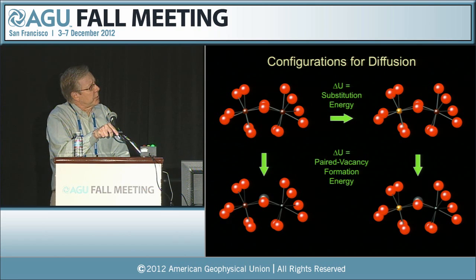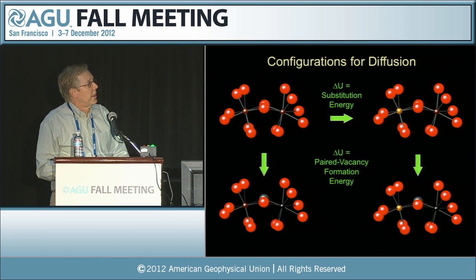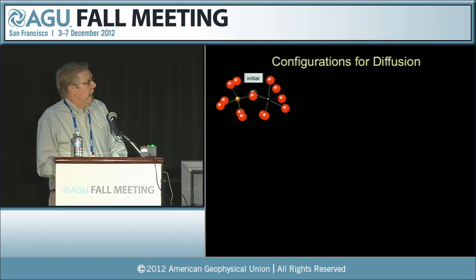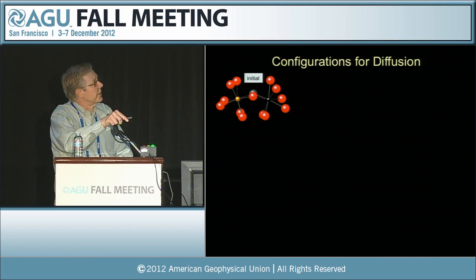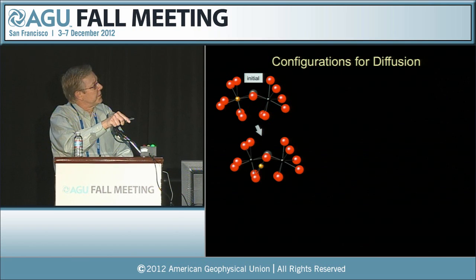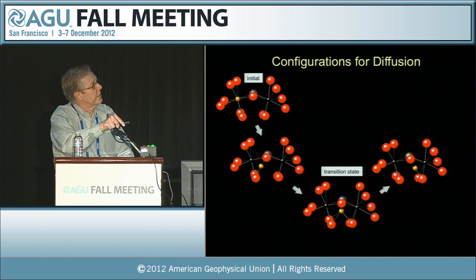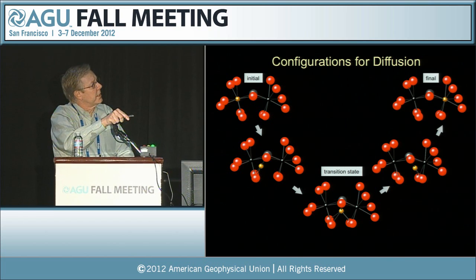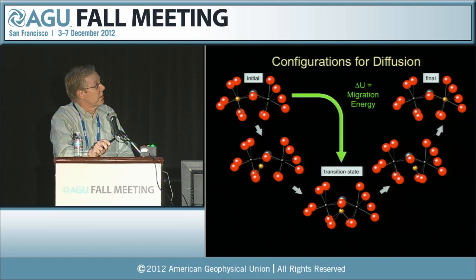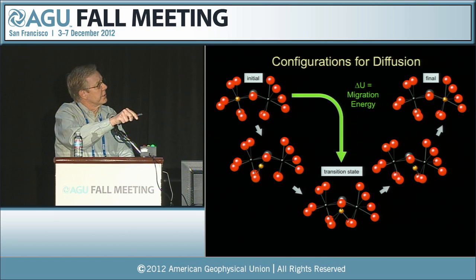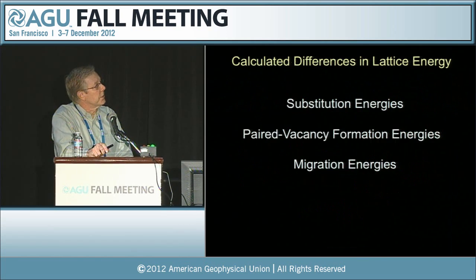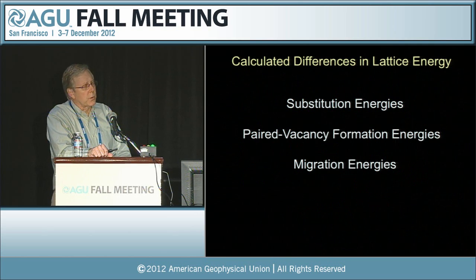In order for diffusion to take place, then we have to have a vacancy over here so this atom can move into it, and that has to be paired with a cation vacancy as well. And so the difference in lattice energy between these 2 states, I'll call the paired vacancy formation energy. And then the diffusion jump itself, if we start off in this initial state, it moves through a path sort of like the one shown here, back to its final state. Those are the same energy. This is the maximum energy along the path, and the difference between the initial state and that state is the migration energy. So these are the types of energetics that we're going to investigate.